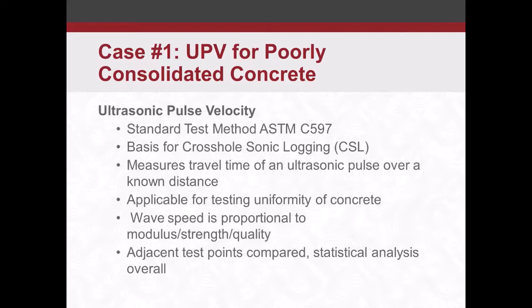One of the things that we do when we use this test method for this application, we typically do it on a grid pattern, maybe a 1 foot by 1 foot grid pattern, maybe 2 foot by 2 foot, depending on how coarse or fine that grid pattern is. We certainly discuss that with the project team and see what their overall goals are. You get obviously finer detail with the finer grid spacing. On this particular project, we did two different grid spacings, a 1 foot by 1 foot and a 2 foot by 2 foot.